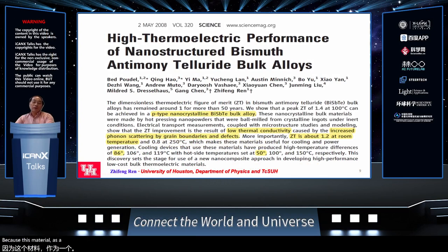Okay, so our first demonstration of the technique was on bismuth antimony telluride, because this material, as I pointed out earlier, maintained the ZT at about 1 for 50 years, and we were thinking it was easily possible to demonstrate this technique in this material with much higher ZT.